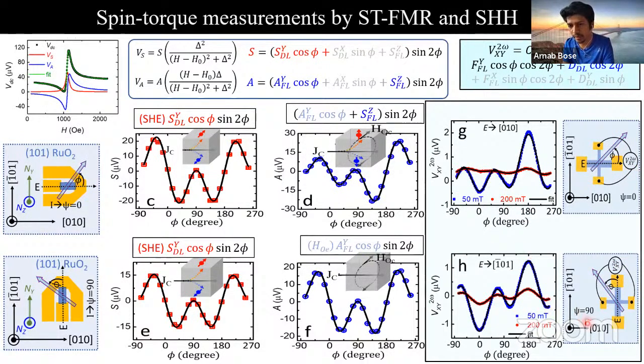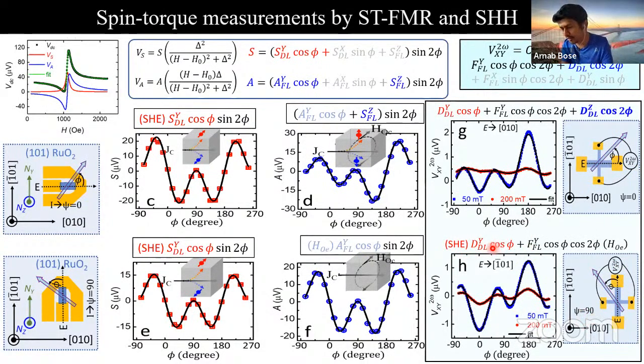So for this case, when we run current along psi equal to 90, everything is trivial. We have contribution from the regular spin Hall effect and Oersted field. However, for this case, the difference in the signal is predominantly because of this cos 2 phi term. Again, suggesting that we have extraordinary torques getting generated due to out of plane spins flowing in the out of plane direction. So the summary is, by doing two independent measurements, we come to the same conclusion that in this ruthenium dioxide 101 plane, we have strong crystallographic axis dependent out of plane anti-damping torque.